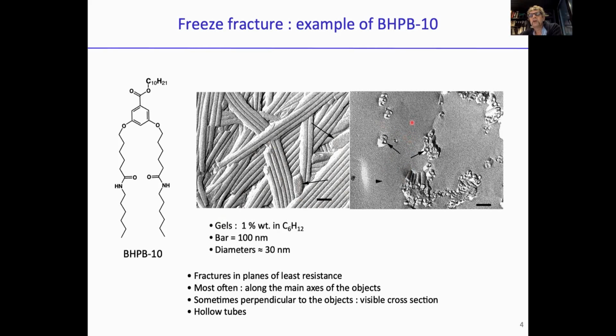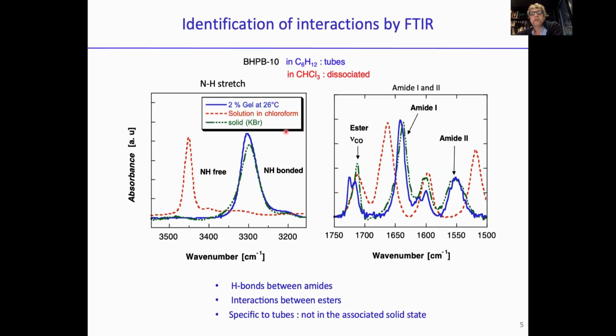You can see here the amorphous solvent, and these are the same objects, but sticking perpendicularly out of the fracture. And on these pictures, because of the fast shadowing effect, you can see that the center of the cylinder is hollow. So in fact, they're not plain cylinders, they are hollow tubes.